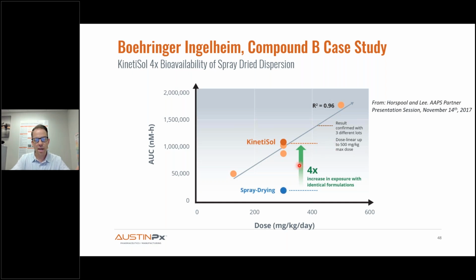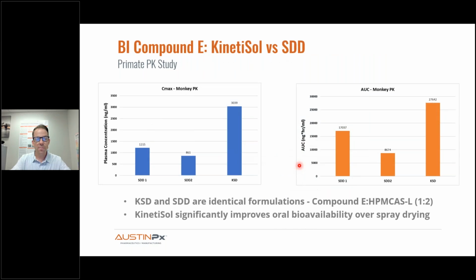And once again, and this is in the literature, we published it, it all comes down to congruent drug polymer release and the density of ASD particles promoting simultaneous drug polymer release, whereas with spray drying, especially with enteric polymers like HPMCAS, the drug is prone to coming out of the particle in the gastric environment or in suspension before the polymer is soluble. So again, we did this with multiple compounds with BI.